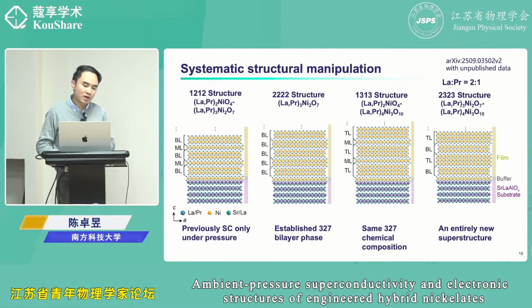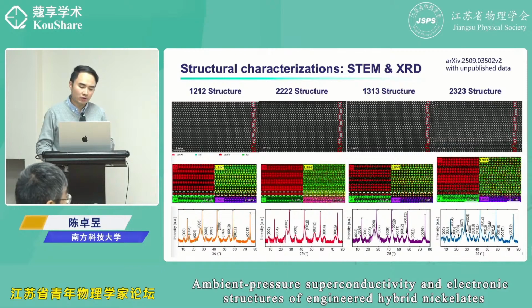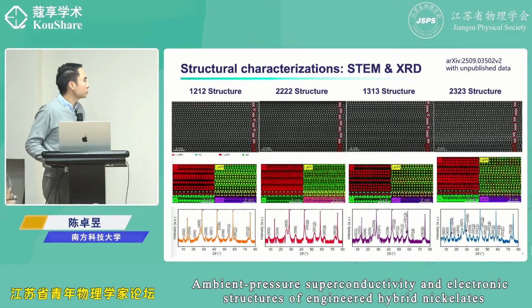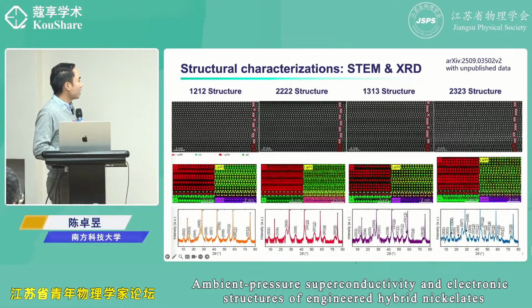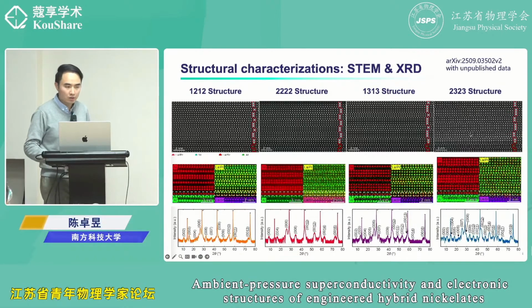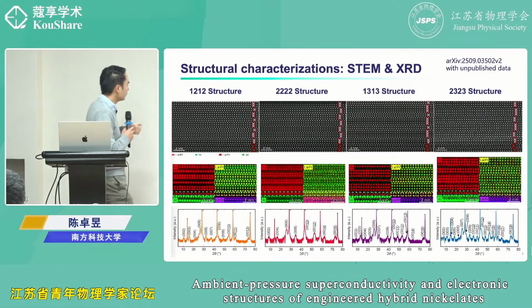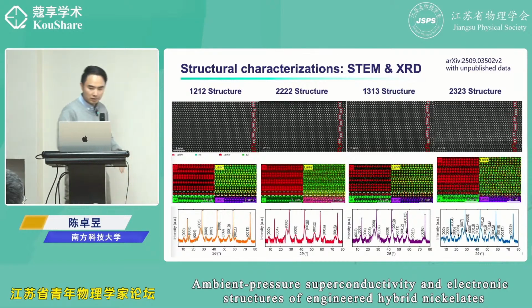So these are the 4 designed structures, and the results show that we get the desired structure. For this 1-2-1-2, you can see bilayer, monolayer, bilayer, monolayer alternating. Also in the EDS, you can see 2 layers of nickel and 1 layer alternating. 2-2-2-2 is all bilayers. For 1-3-1-3, you get 3-1-3-1 alternating, and for 2-3-2-3, you get 2-3-2-3 alternating. These are smaller-range TEM. Lanthanum praseodymium is this one. All these 4 structures look nice.